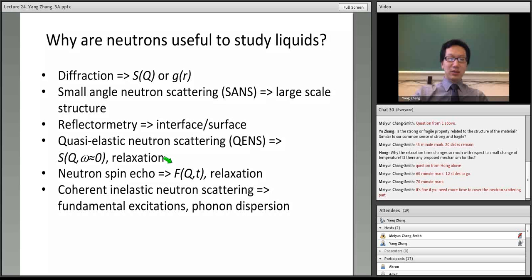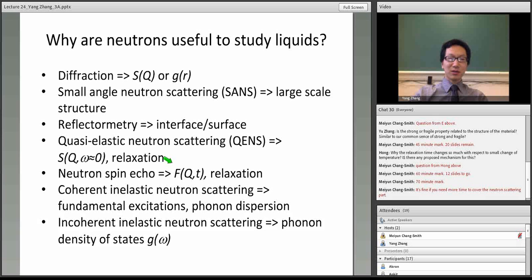And by doing coherent inelastic neutron scattering, we can detect the fundamental excitations like the phonon dispersions. And by doing incoherent scattering, we can directly detect the phonon density of states.